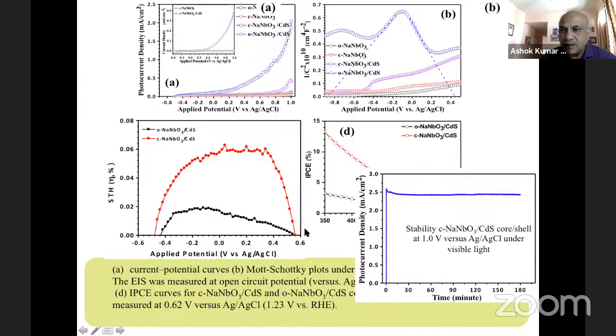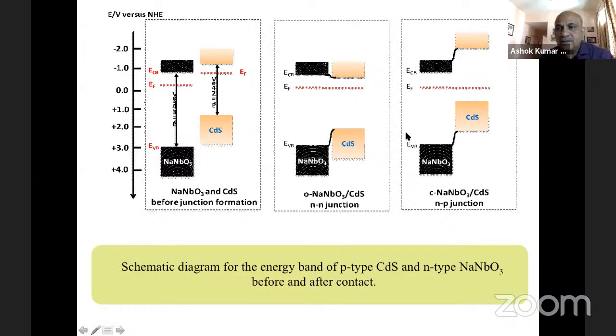ratio. Okay, so now you can see that the design of the particles matters. This is something that is very stable, etc. This is the theoretical understanding of why this happens. Why this happens is because in one of the systems, you create an NN junction, whereas in the other one, you create an NP junction. And this NP junction is much better, more viable, and gives you more charge separation. The electrons and holes can be separated easily, whereas here the electrons and holes are not separated. The electrons are both on cadmium sulfide, and the holes are on sodium niobate.